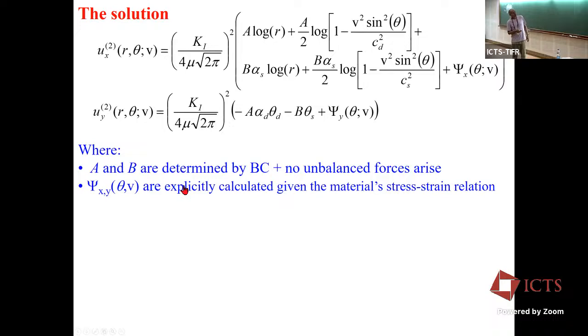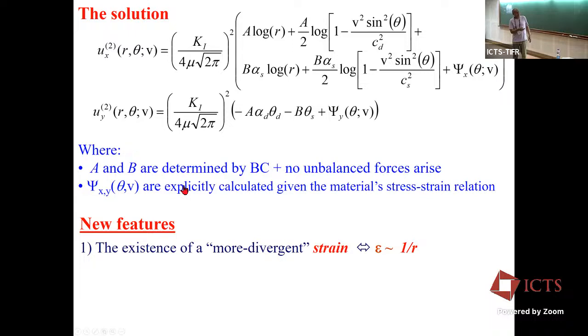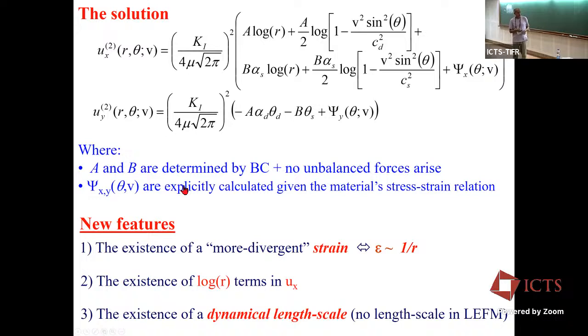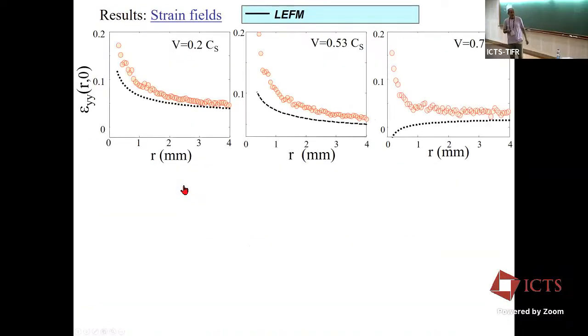You can stare at it all you want, but the salient parts of the solution are that, instead of regularizing the square root singularity, the singularity becomes worse. It becomes like 1 over r instead of 1 over the square root of r when you take into account nonlinearity. It also has logarithmic terms in the displacement along x, and you get a dynamic length scale that depends on the nonlinear coefficients, on the second order nonlinearity.